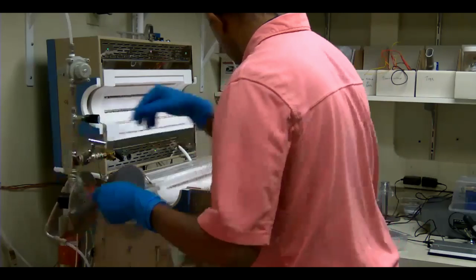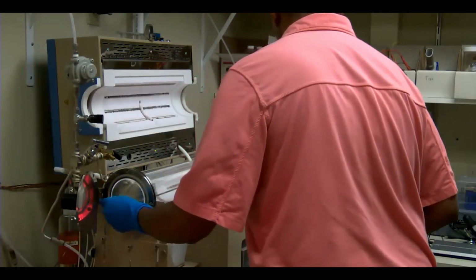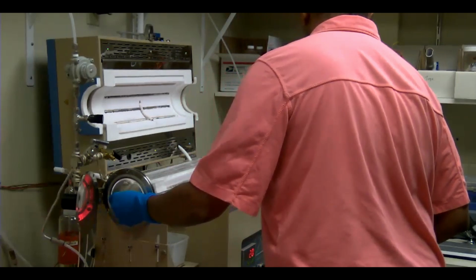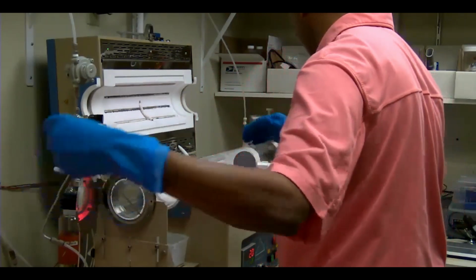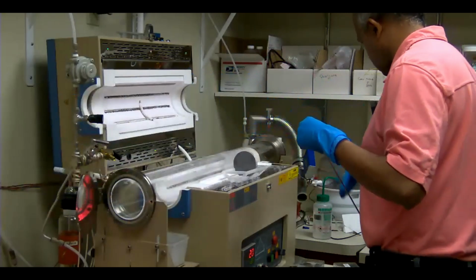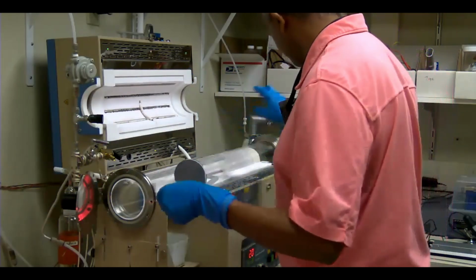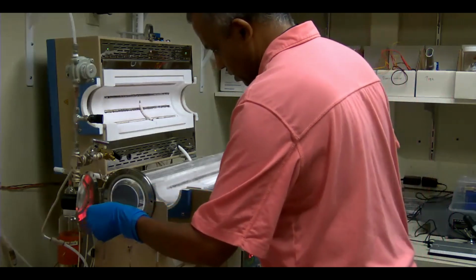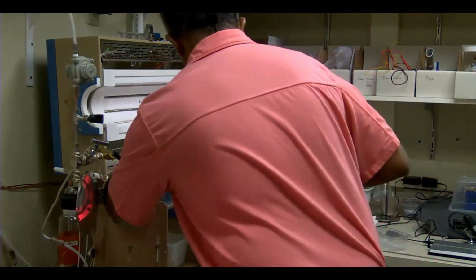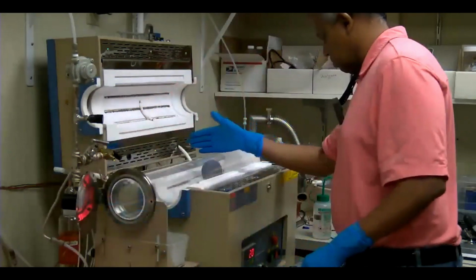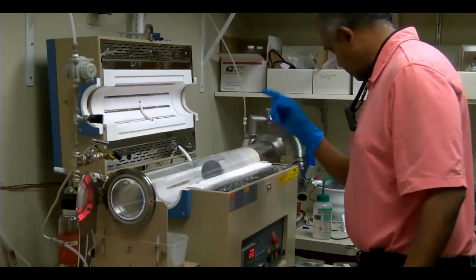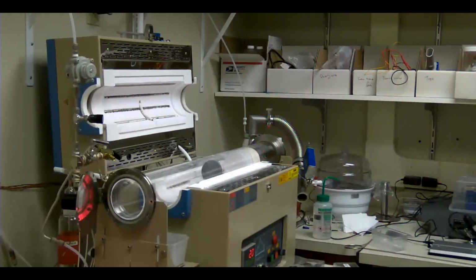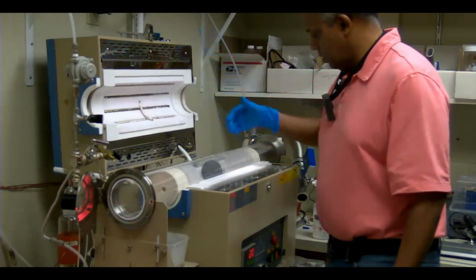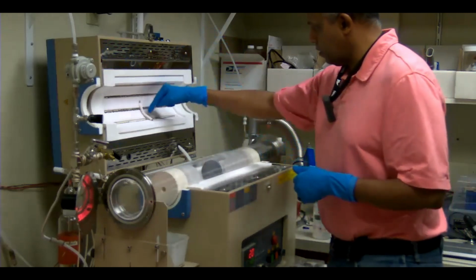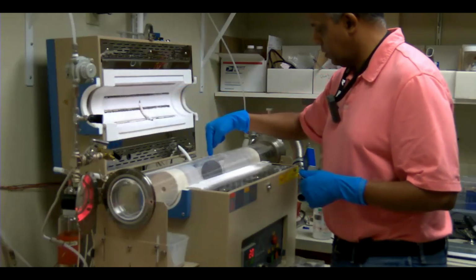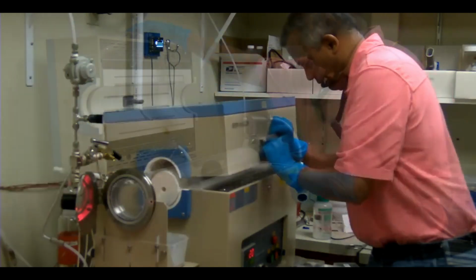So before I do that, I have to put in the baffles. These are insulator blocks, one on that side, so that prevents excessive heat from flowing to the output. All right, so we put in the temperature baffles, and here is the wafer. We move it approximately to the center of the furnace, and then more thermal baffles on the other side. There are heaters on the bottom and heaters on the top, and there's a thermocouple here that's touching the glass, and that's what's measuring the temperature.